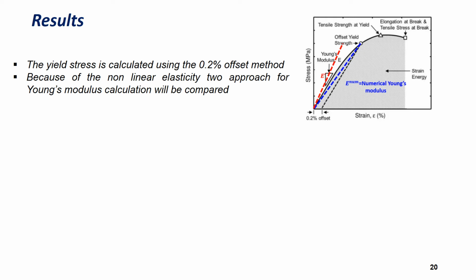Now we go to the results. Reaching the plastic limit with proper stress and strain levels is crucial for our study. Since the ABS presents a non-linear elastic behavior, two methods will be used to calculate Young modulus. The first one is a calculation as a slope of the tangent of the true stress-strain curve at a low stress. The second considers a linear elastic behavior that goes until the yield stress point.